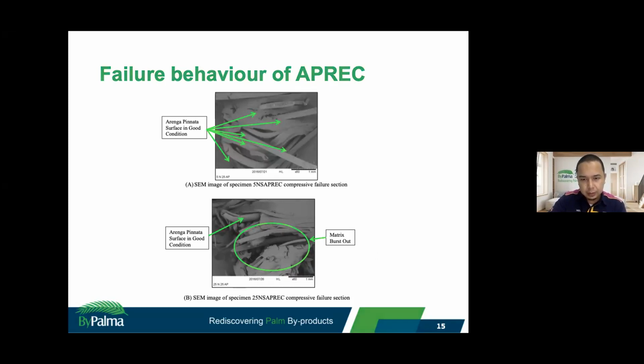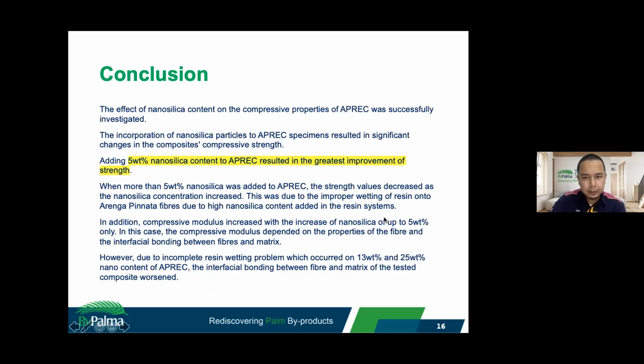As you can see, the epoxy matrix burst out after the test. This means that compared to the 5% and without nanosilica specimens, the epoxy became more brittle. Besides, the Arenga Pinnata fibers also seem detached from the epoxy matrix, showing a lack of interfacial interaction between fiber and epoxy matrix. As a conclusion, the addition of 5% of nanosilica content to APREC